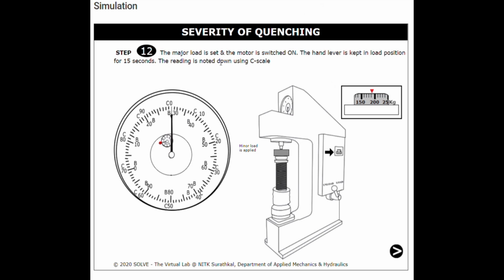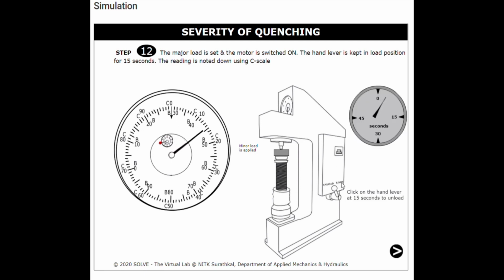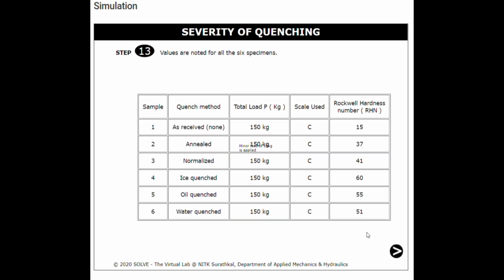Since the major load is set and the motor is switched on, the hand lever is kept in the load position for 15 seconds. The reading is noted using the C scale. After 15 seconds we have to unload. This is the result we obtain for all the 6 specimens.